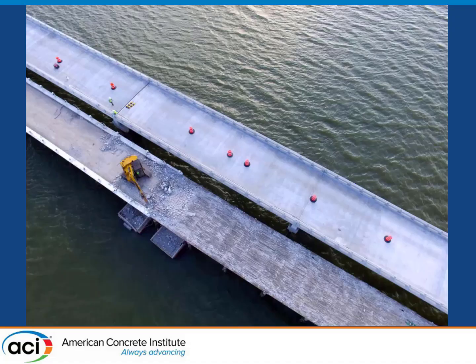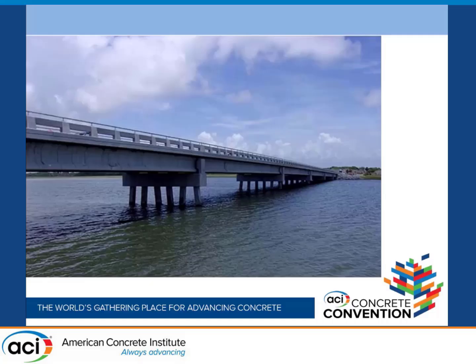And of course, after the new bridge was finished, the old bridge was demolished and removed. And in all the years that I've been in the lightweight business and in the concrete business, we've observed that lightweight concrete in bridge decks and in other applications just lasts longer than normal weight. And so, over the last 30 years, there have been a lot of studies on internal curing that have proved that internal curing targets and mitigates the cause of these cracks.